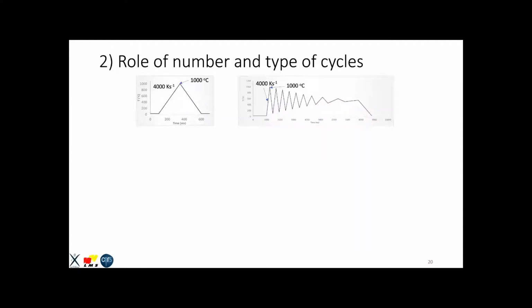Next, we studied the role of number and type of cycles. We did one cycle up to 1000 degrees at 4000 Kelvin per second, heating and cooling. And then we did the same first cycle, but we continued cycling at lower temperature rates and amplitudes.